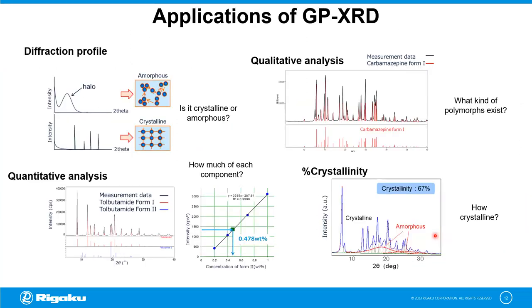With this general purpose XRD, we can learn quite a few things about the sample. We can learn if it's amorphous. If you see a halo, it's not crystalline. If you see these nice sharp lines, that indicates that it's crystalline. From there, we can do a qualitative analysis. Do we have more than one form of the material in there, a polymorph?